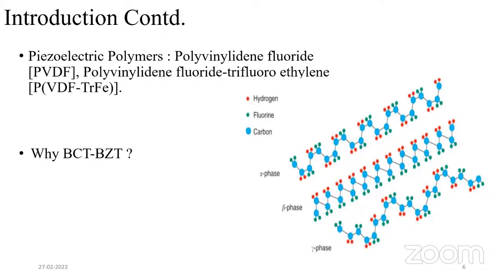Now the nanomaterial used was BCT BZT. Why I chose BCT BZT is because it is an environmentally friendly piezoelectric ceramic that is a promising alternative to lead based piezoelectric material PZT, whose toxicity is well known. To achieve beta phase, there are so many ways to enhance it. One of them is adding nanofiller. So the nanofiller I used is BCT BZT.